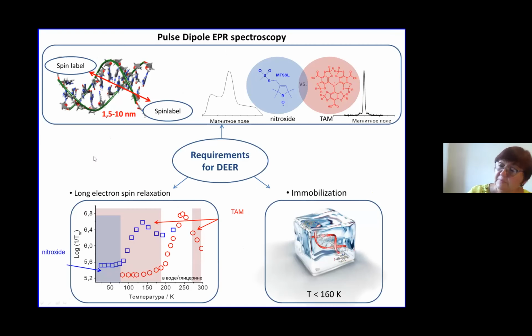So like 6 years ago, we aimed to develop an approach to measure the distances at room temperature. Why was that interesting? Because, as I told before, dipole-dipole interaction is the main point. And if we measure this in liquid, then dipole-dipole interaction will be averaged and we can't see anything. So because of that, all these experiments are done in frozen solution at very low temperature. And the question about how reliable these distances are appears. As a rule, nitroxide is used as a spin label, and what we proposed was TAM, the trityl radical.